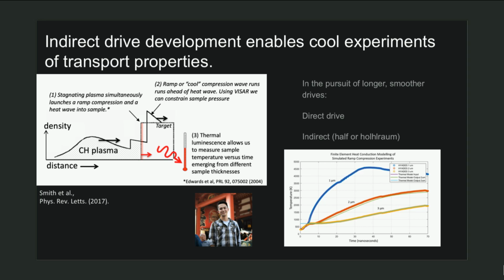And so instead of just directly blasting your lasers at the material, you can blast them on the inside of a hohlraum, which is a gold tin can, basically. That turns into a super hot material and emits X-rays. Those X-rays hit your sample, and that could be a way to drive your sample to high pressures. Or you could even do it one step further, where your tin can irradiates a brominated plastic layer. That turns into a plasma, propagates across a vacuum gap, and hits your sample very slowly, like snow. This is like a Rube Goldberg type of device. So these are different ways that we try to smoothly bring pressure up.